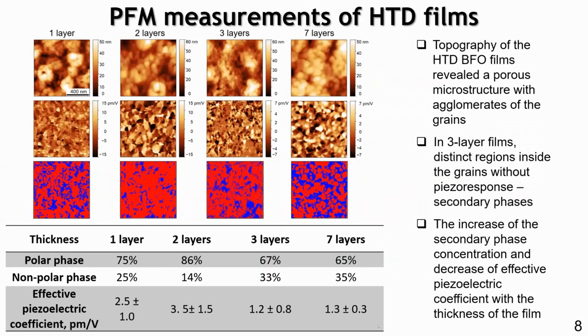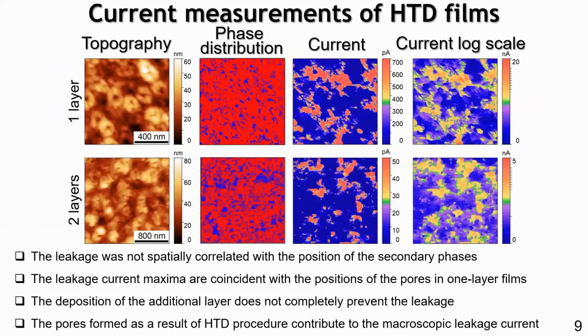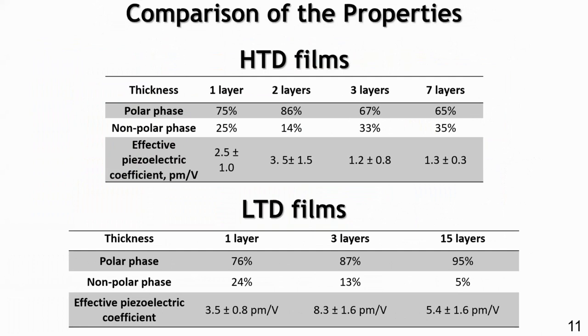Let me show on these images. So the liquid phase can really create channels in the film which are responsible for the pores. It's just a process of evaporation, really fast evaporation. In the case of low temperature and long time drying, we have quite uniform removal of the liquid from the film, and the coverage of the film doesn't create these pores or cracks in the material, and it allows us to create a more perfect, morphologically perfect structure. And it makes sense for the further crystallization process and useful properties of the film.